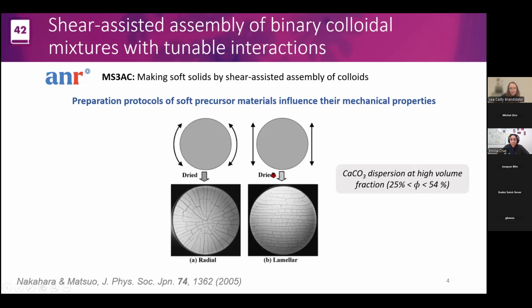And then the bucket that was stirred back and forth reveals this lamellar structure. So we already start to see that we can assist some certain assembly by shearing. There's a memory that remains in the solid particles that were dispersed in this soft material.